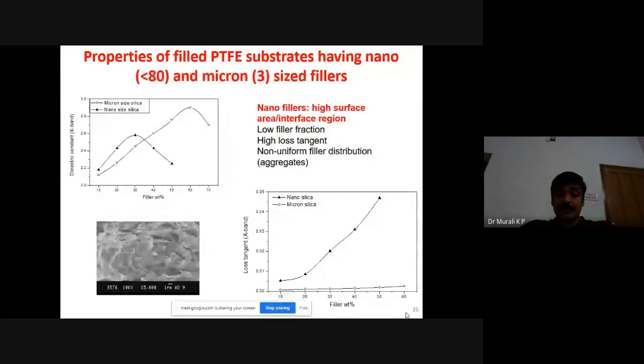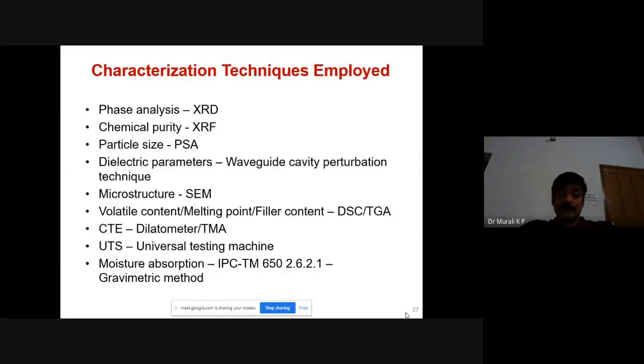So what I was telling, nano size fillers, it is better to avoid when you fabricate a microwave substrate. Now the characterization techniques, just to mention: phase purity of the ceramic filler using XRD, chemical purity using XRF, particle size of the filler because it is very important, dielectric parameters using waveguide cavity perturbation technique, microstructure using SEM, and DSC, TGA for volatile content, melting point, or filler content of the polymers.